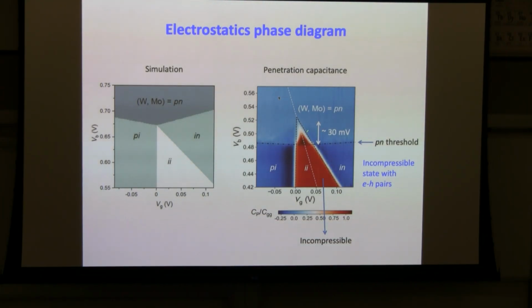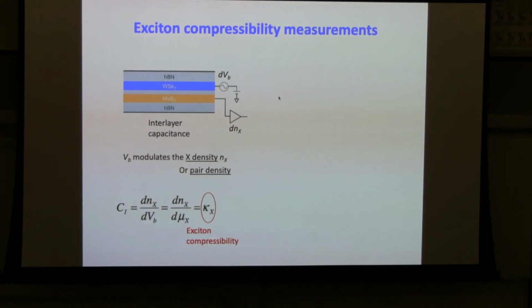So now it already suggests that maybe in this triangular region here, we get a charge incompressible state, but somehow there are already electron hole pairs in the system, and that would be just the excitonic insulator that I'm talking about. To show that there are indeed electron hole pairs in this region where the system is incompressible, we can come to another measurement, called the interlayer capacitance measurement, which directly measures the exciton compressibility. What we do in this measurement is apply an AC voltage of dVB to one of the layers and collect the displacement current from the other layer.